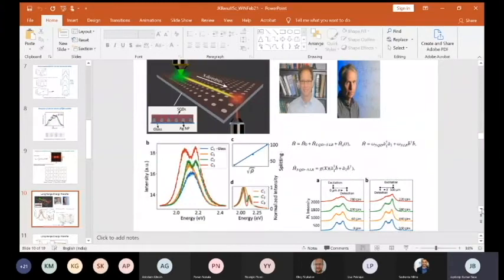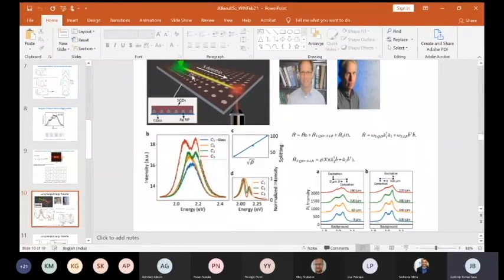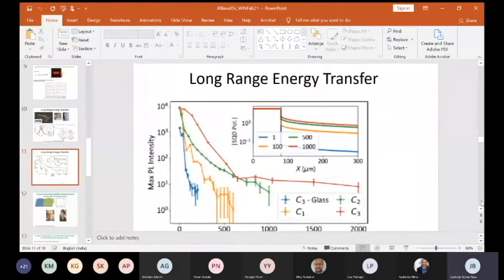What was remarkable in our case is that even if you go very, very far away from this excitation region, you still see evidence. What I'm showing here are spectra collected at different regions, and it's reversible. If you excite here and collect here, or excite here and collect here, the behavior is roughly similar. You see this strong spreading, which means that these polariton modes are propagating far away from the excitation region. To quantify this, we extracted a distance, up to which you are able to see the emission from the quantum dots although they are excited at a remote location.